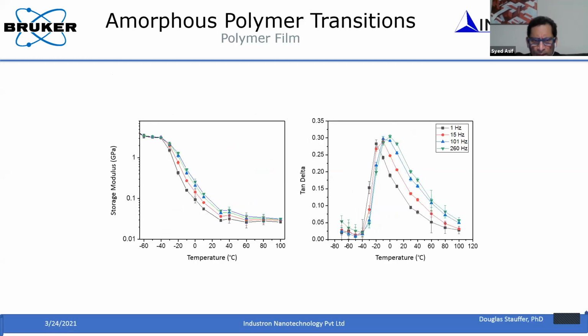Okay, so this is another example, for a polymer thin film, which is very difficult to do with any conventional DMA technique, but we can do it at the nanoscale. By doing this method, we can measure the storage modulus as a function of temperature, from cryogenic temperature to a higher temperature, and we can also calculate the tan delta as a function of temperature. From that, we can determine the peak position, the glass transition temperature, and all of that.